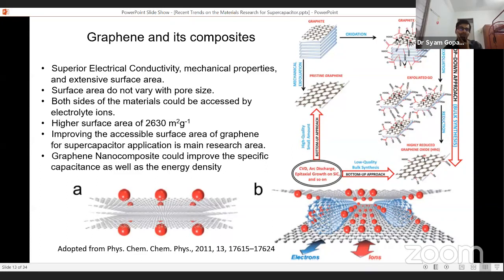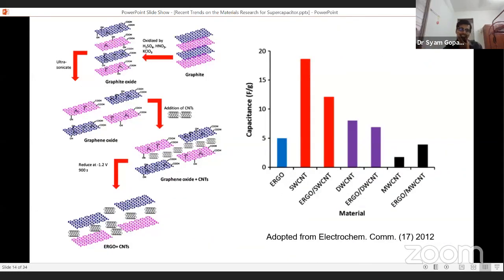But the beauty of the research is that another group reported that this addition of carbon nanotubes to graphene oxide does not improve the capacitance of graphene at all. Why? Because they are saying that only the average capacitance value is increasing, and the capacitance value of graphene itself could not be increased by the addition of carbon nanotubes. Like that, there are plenty of research problems in graphene, if we look.